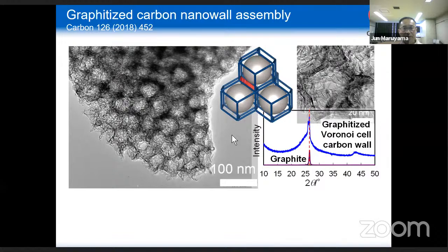If we use polystyrene nanoparticles as a pore template, I can make very three-dimensionally ordered porous carbon materials. And these walls can be graphitized easily, and these walls also have the ability for lithium storage.